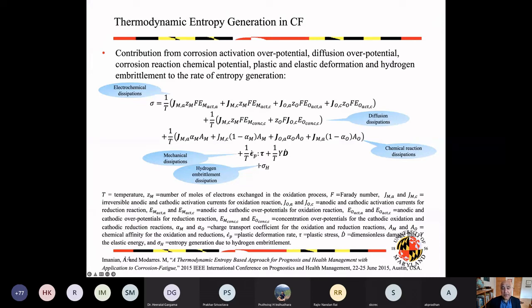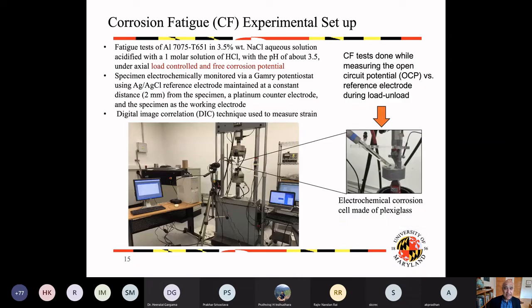This term shows the amount of mechanical dissipation. This shows the embrittlement, any hydrogen embrittlement that we have. Okay, so generally speaking, this is the equation for corrosion fatigue, the thermodynamic equation of corrosion fatigue, which interrelates these terms with each other. And this is an example of one of my testing labs, which you see here. I'm fatiguing. I do experiments also. As I said, I'm both an experimental and theoretical person.